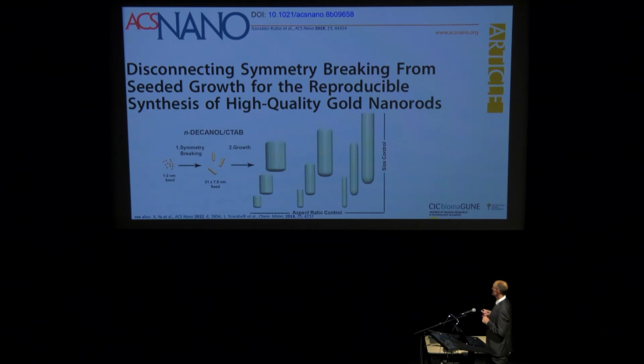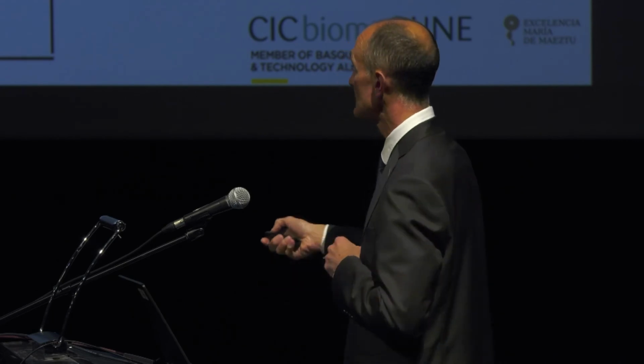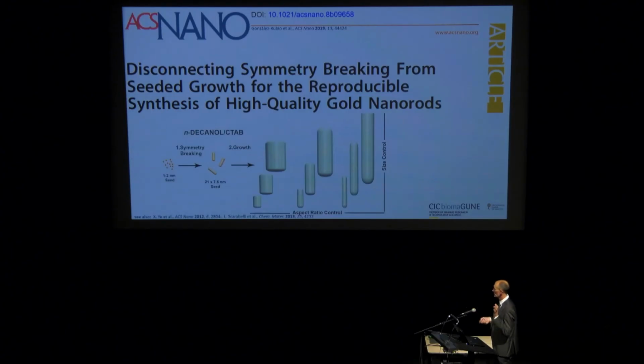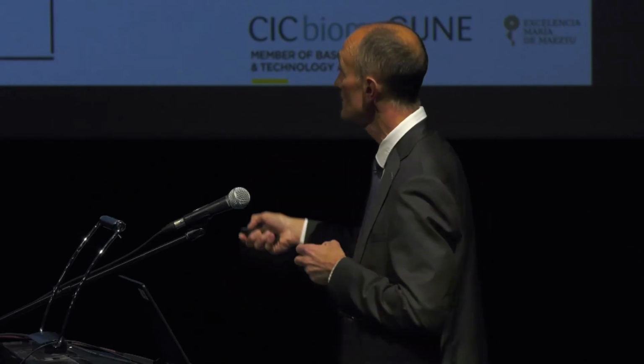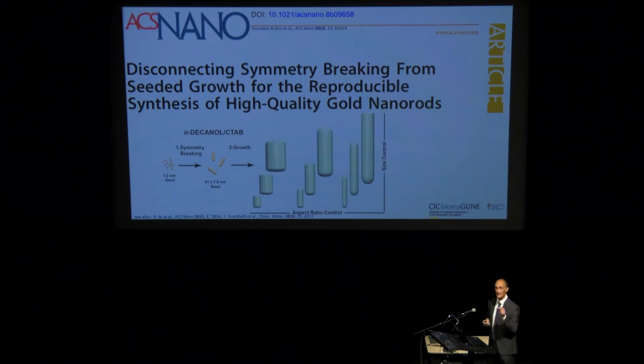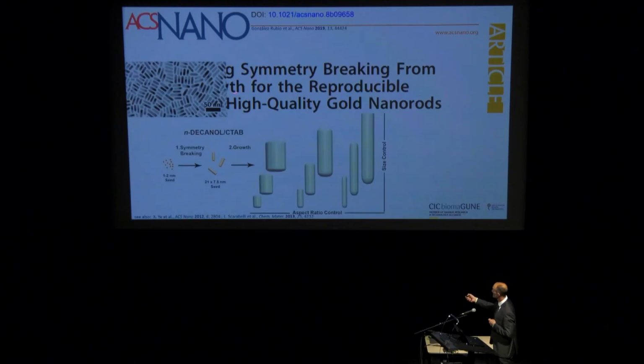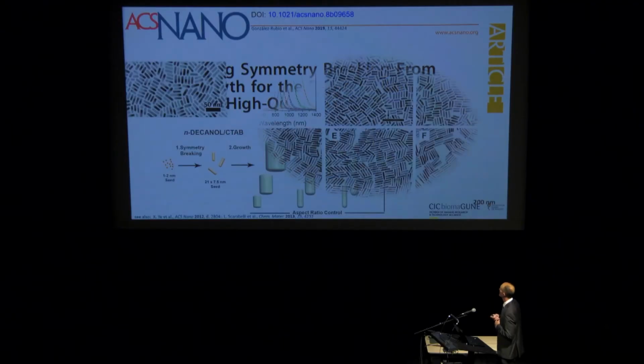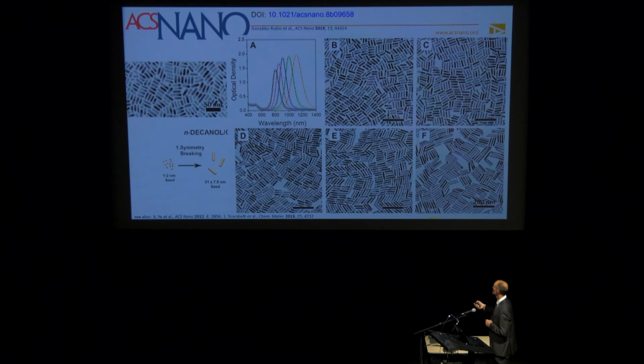Another way to improve monodispersity is the use of co-surfactants. And this is again the work of Guillermo, where, following work from the lab of Chris Murray at the University of Pennsylvania, Guillermo proposed that by using n-decanol, you can use it already in the initial stages and go from very tiny seeds, which are roughly spherical, as I showed you, into elongated seeds, so very tiny nanorods, that can then be used to grow larger nanorods with predefined dimensions. And so by starting with nanorods like this, very thin ones, less than 10 nanometers in diameter, you can actually grow basically anything you like, with extremely well-controlled dimensions, with very narrow plasmon resonances.